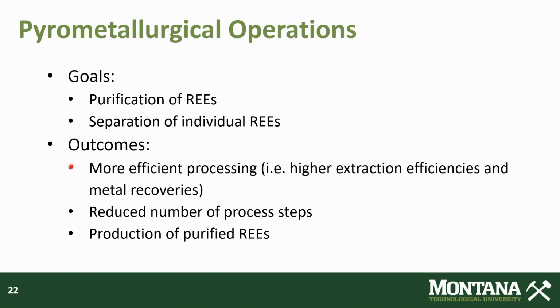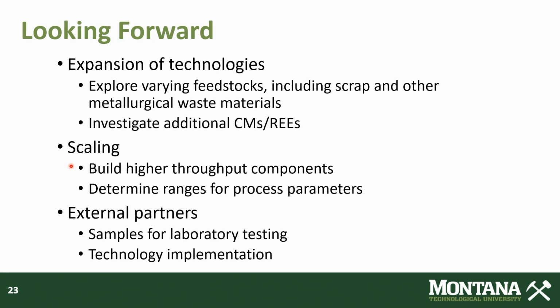Some of the outcomes already realized: higher extraction efficiencies and metal recoveries in the roasting and leaching step. We can dramatically reduce the number of processing steps necessary in order to recover and separate the rare earth elements. And again, I've already talked a little bit about the production of the purified REEs. So looking forward, we've been working with surrogates and a source sample. We're looking for alternatives to feedstock. We want to be sure that this works on a variety of mineral concentrates. We want to look at scrap, anything else that has an appreciable rare earth content that we can bring back into the process. And we'll also look at maybe some other critical metals that might be effectively recovered through a similar process.